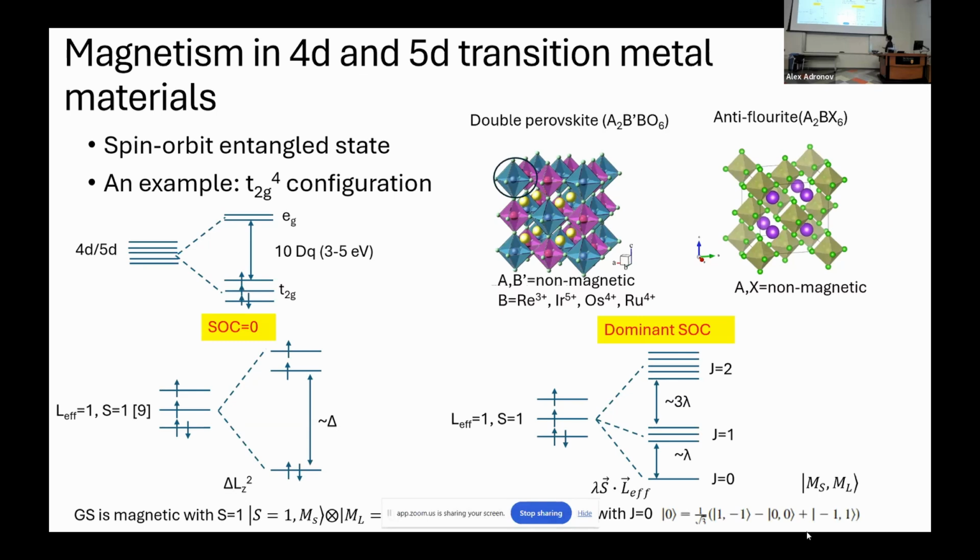You have basically a spin of 2 electrons, so S equals 1. And depending on where this down spin is, you have an orbital degeneracy of 3. So in the language of orbital angular momentum, you can rewrite it as an effective orbital angular momentum of 1. All right, this is a nice state. This is probably the best we can do in simplifying our problem.